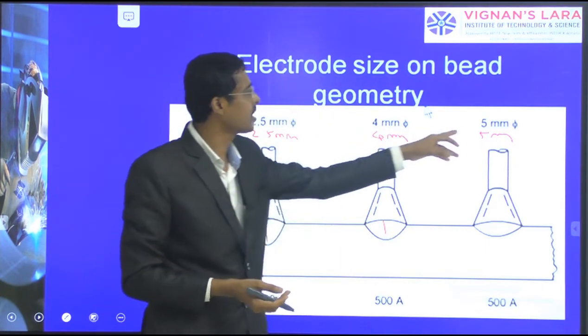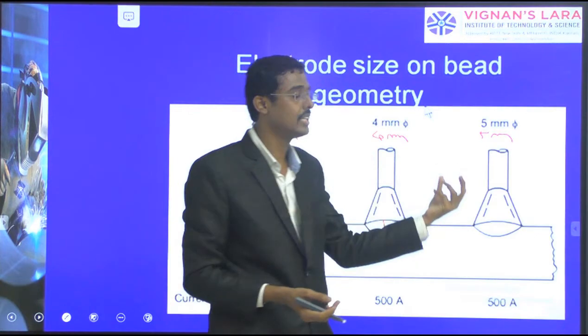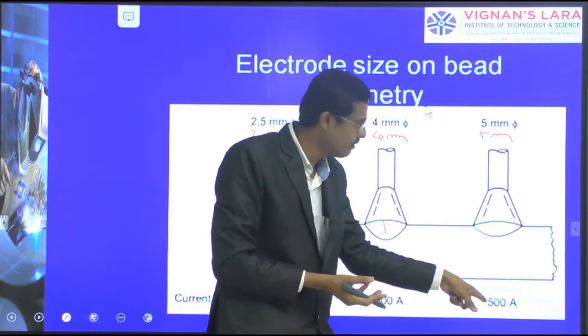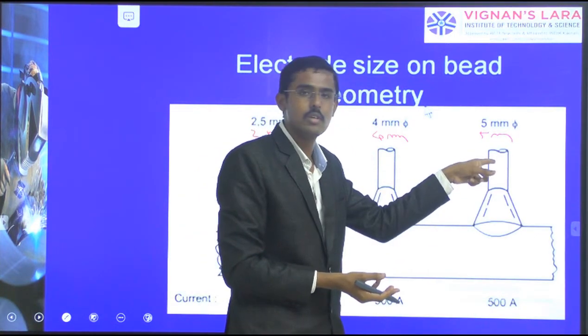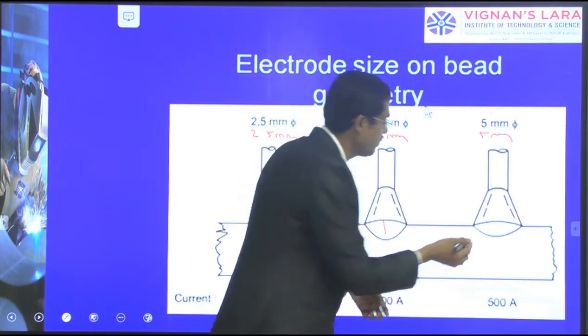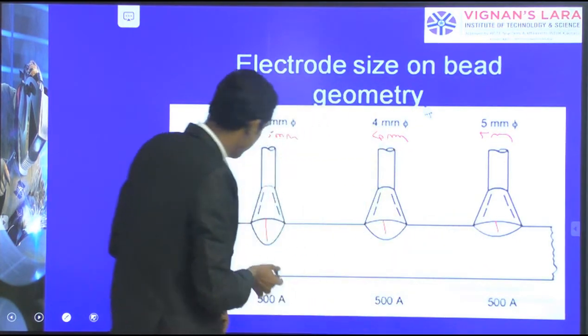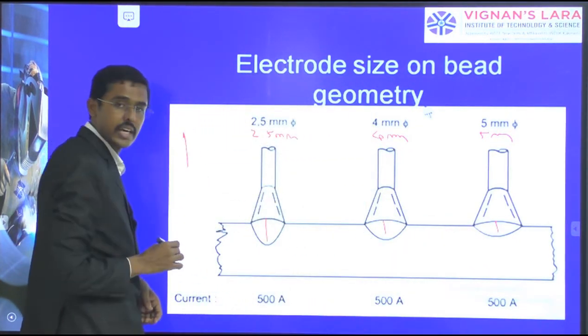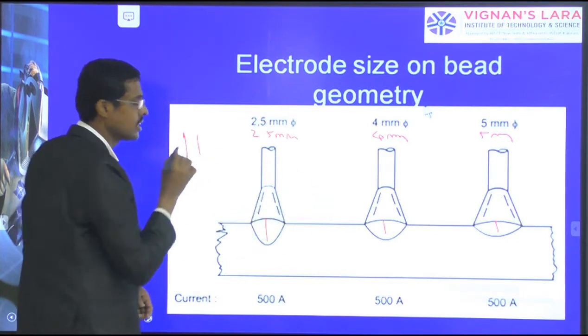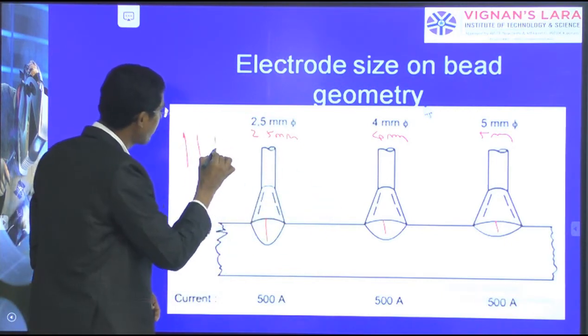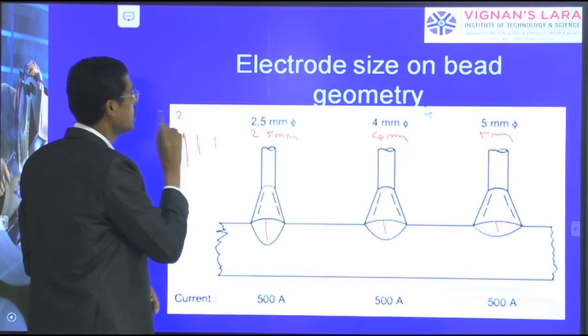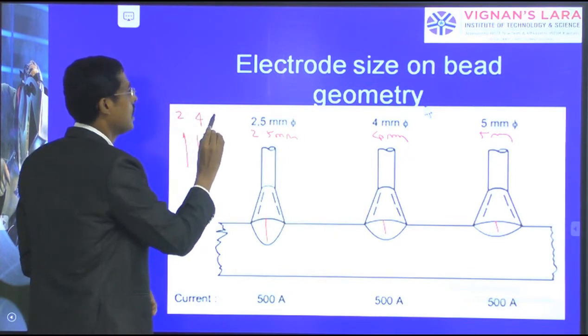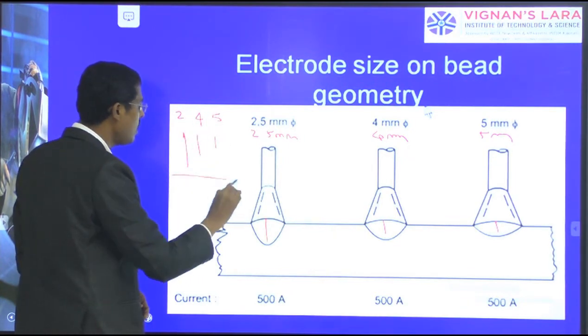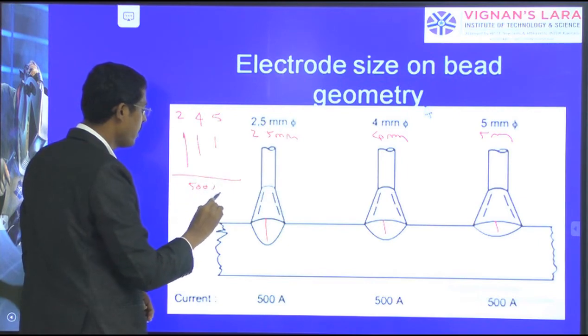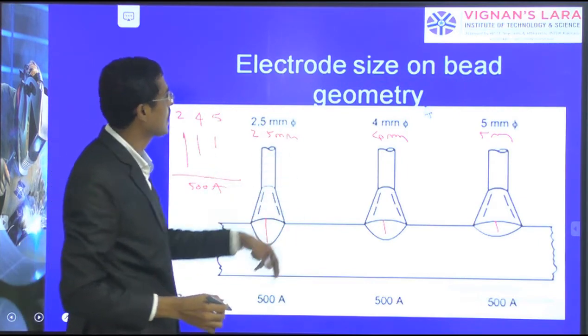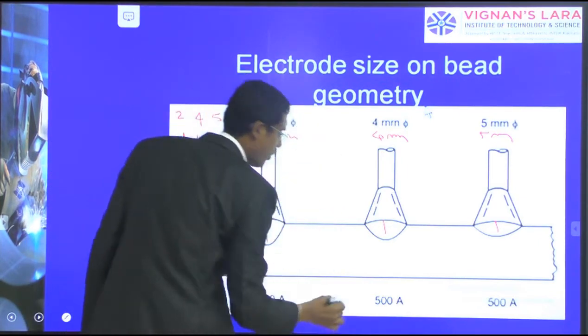And now further I am increasing, for example, 4 to 5 mm. The diameter is further increased, but the current is given the same. It is not possible to melt as per the given current. What happens? Again it decreases. From here the penetration is like this, in the second condition it is reduced, and in the third condition it is further reduced. I have used 2.5 mm, 4 mm and 5 mm electrodes, all for 500 amp of current. So optimized current is to be given.